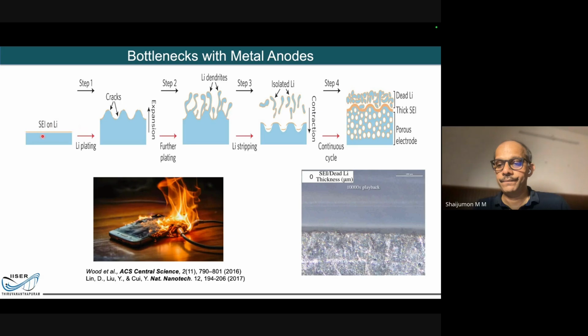If the surface is not very uniform, there can be a crack in this film. And if there is a crack, all this lithium will start forming as dendrite. You see, this lithium forms as dendrite. And sometimes it gets detached from the surface of the lithium and becomes isolated or dead lithium, which no longer takes part in the cycling, in the reaction process.